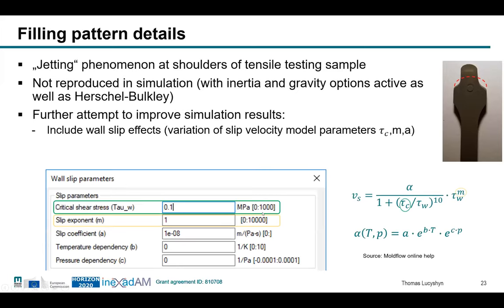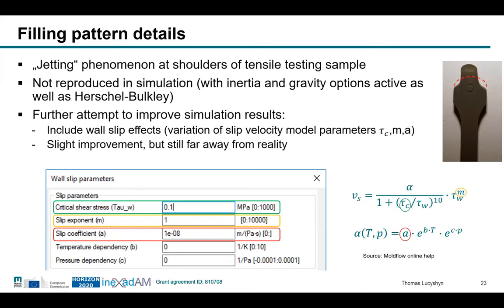So we played around with these parameters just as a parameter study, not with real values, but in the end we found out there was a slight improvement. So the shape of the melt front improved or was showing a similar behavior, but not really the reality. But at the same time, the pressure results were so unrealistic that we stopped this. So there are really some issues that are not yet solved. So we are working on this to improve.